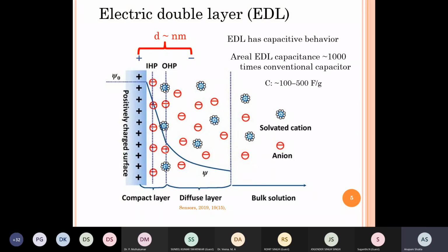Second thing is, remember this is again a surface phenomenon. So if I increase the surface area, then I get an additional increase in the capacitance. So in the electric double layer where you have liquid, it is possible to consider electrodes which are porous. And when you have pores, because the electrolyte can enter into the pores, there is not much that one can gain in a completely solid state device by making the electrode porous. On the contrary, one will only lose there because the conductivity will go down. But here, by making the electrode porous, the surface area can be increased by 3 to 4 orders of magnitude, or even higher. So both of these combine to give a very large increase in the capacitance. And people have reported 100 to 500 farads per gram for various types of material. In fact, the reports are even higher, as we will see when we proceed into this talk.